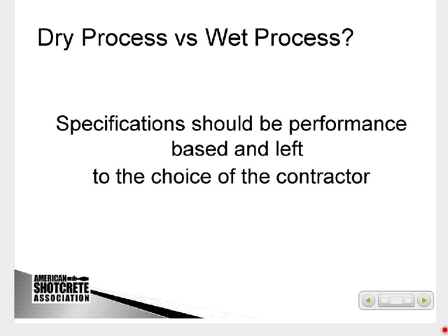And a lot of times the owner, or an engineer, will ask, should I specify dry mix or wet mix? And it's really dependent on the experience of the contractor and the type of project. If I'm on a repair job that has a lot of stop and start, dry mix is good because I haven't hydrated it. The water's not introduced to the mix until it exits the nozzle. So we can stop at any point without having a lot of material stuck in the hose that you have to get rid of. If you had wet mix at that point, you'd have to clean out your hose every time that you stopped and then restarted. So it really depends on the process, on the application.